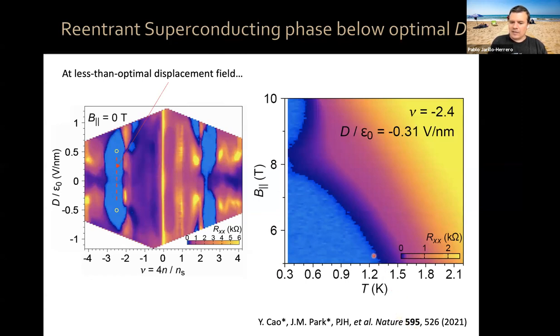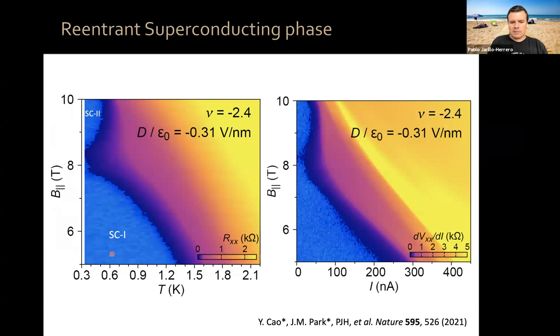What we see is that TBKT, this light blue region tells you where zero resistance is. So TBKT here goes down with parallel magnetic field, reaches sort of zero, and then starts to increase again at finite, at higher magnetic field. Okay. This is called reentrant superconductivity. It cannot be explained by any of the other mechanisms that I mentioned, to the best of my knowledge. Okay, we can see that there are superconducting one and superconducting two regions, phases, as a function of magnetic field. This can be seen not only at the level of TBKT, but if you also measure the critical currents, the differential resistance versus current bias, you can also see that the critical current decreases and then increases again, okay? And you have these one and two regions.